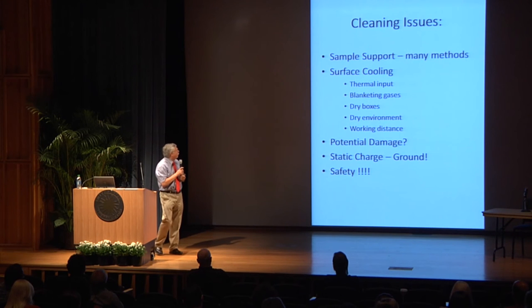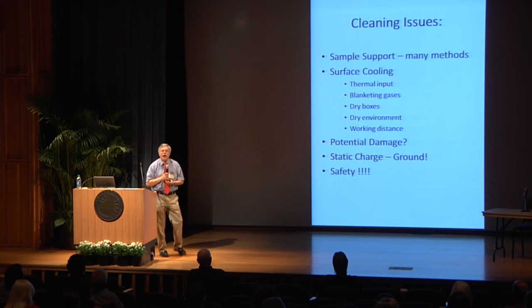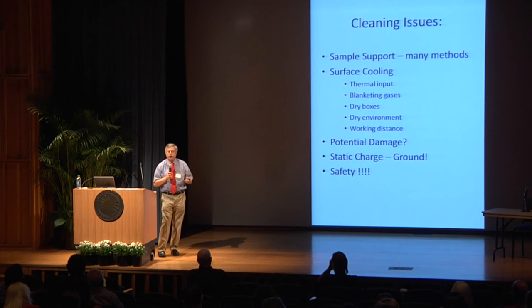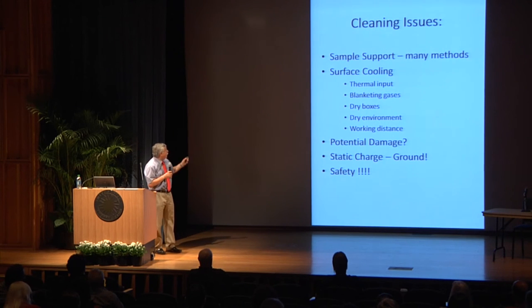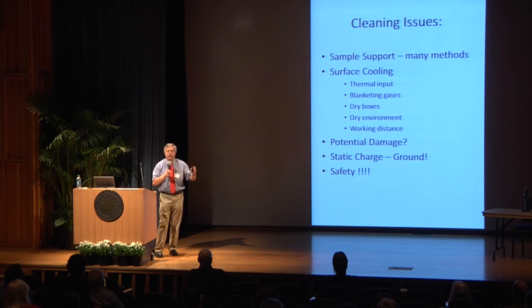Another way of getting around this problem: dry boxes, dry environments, essentially having a mini environment where the moisture is low. Generally, I think for this audience, you get away with maybe 1% relative humidity for cleaning a polymer object. But in the semiconductor industry, they need it down to parts per million moisture. Another trick is working distance, increasing the distance from the nozzle exit to the surface. You start compromising some cleaning, first the hydrocarbon removal. But if that's okay, you still could do particle removal and not cool the surface that much. So it's an effective way of trying to reduce this moisture problem.